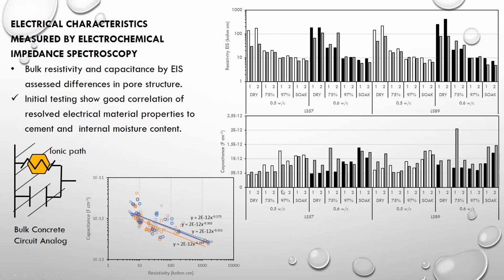So by observation, we can see that when the concrete is wet, the wet resistivity corresponds to expected behavior, where we have the lower quality concrete with the higher moisture content have a lower wet resistivity, and that's for all cases with the rock. The capacitance shows similar behavior in the wet condition. Ideally, we'll see a higher capacitance that's related to the higher capacity of water, for example. The dielectric of water is much higher than that of the aggregate or the cement itself, so that's to be expected.